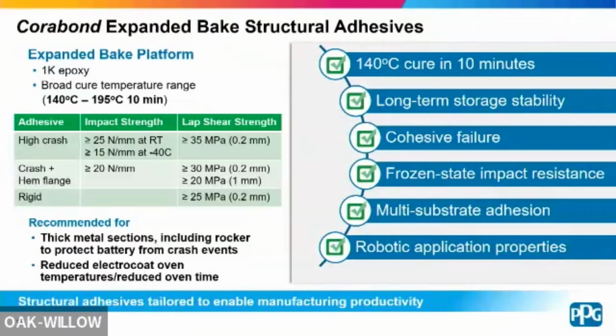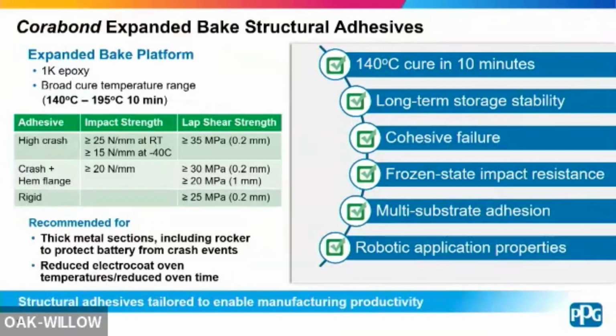For the high crash, just wanted to call out, we've spent a lot of time innovating around that frozen state impact resistance, so at negative 40C, making sure you get above 15 newtons per millimeter strength there. All of these products would have that 140C cure in 10 minutes, minimum bake, with long-term storage stability.